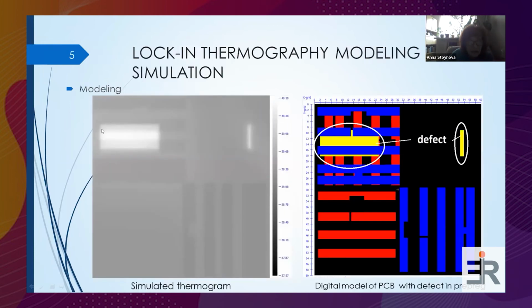Here are the simulation results, and you can see here the copper layers and the defects in the prepreg material. The yellow areas are defects in prepreg. Am I correct? Yellow indicates the defects in the copper material? No, yellow is defects in prepreg material. Red and blue are copper layers. In black you can see the prepreg material. This is a 2D picture of the model.